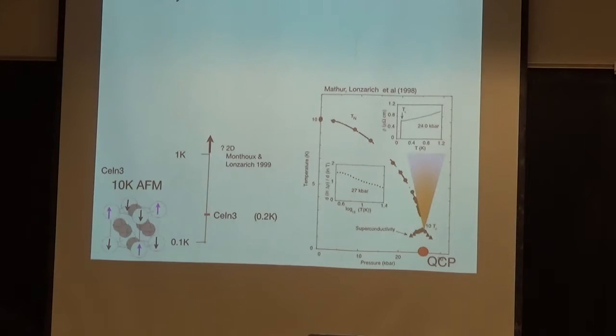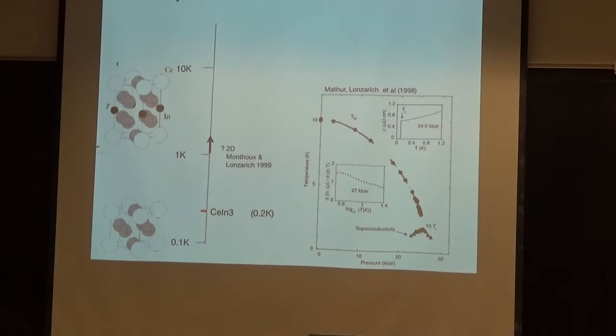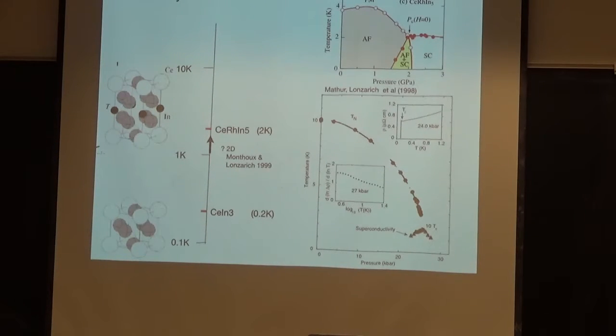And so based on this, discussions went on, and Zachary Fisk and co-workers said, well, that's a good idea. Let's make it more two-dimensional. Let's put in layers of indium something in between cerium indium 3. And so they came up with cerium rhodium indium 5, which is a 2 Kelvin antiferromagnet. And when you put pressure on that, that then forms a 2 Kelvin superconductor. In fact, this has been a subject of great discussion, this material. It's very reminiscent of cuprate superconductors, only in miniature.